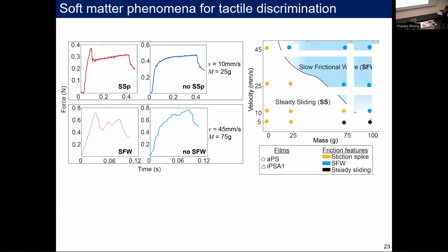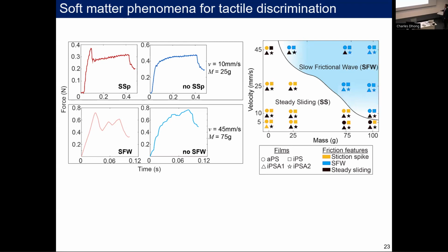Sorry for this butchered figure, but I'm just trying to make it easier to see. So the color represents the type of friction feature. And right now I'm only showing circles. So for APS, you can see that there's this transition between the presence of a stiction spike. Here, there's no stiction spikes. And here, the presence of slow frictional waves. So what I can do is I can look at my other materials and map out where these actual instabilities and transitions in instabilities occur. So what you can see, for example, here is that this circle and this triangle are a different color. So these two materials are experiencing a different type of instability under this condition.